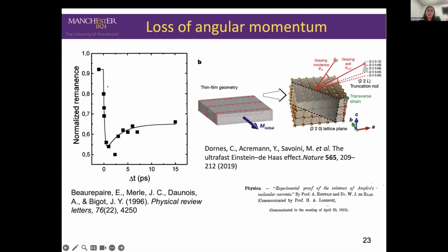During the laser pulse excitation, there's also a loss of angular momentum, as shown in one of the initial experiments on nickel. In 1996, ultrafast demagnetization was shown on nickel, with an abrupt change in magnetization and hence a very quick loss of angular momentum. And for a long time, the community was intrigued by where this angular momentum goes. Only recently, it has been shown that it can go at ultrafast timescales to the phonons. So you can create these local strains in your systems, and then the dynamics of phonons will further evolve, and you can observe what's called the Einstein-de Haas effect.